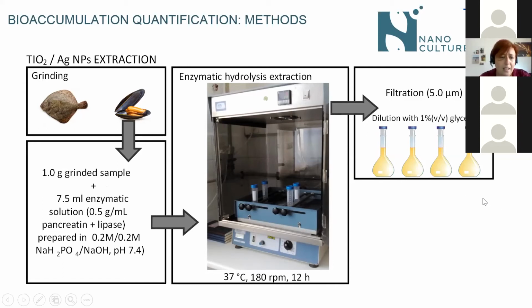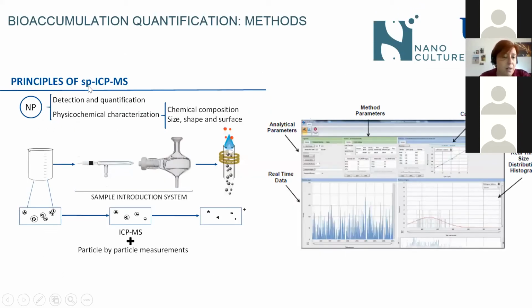And that's why we use mainly enzymatic digestions. Then we filtrate and we analyze using single particle inductively coupled plasma mass spectrometry. This complicated name of technique allows us to quantify nanoparticles by flowing the sample in the detector, and we will obtain peaks. These peaks correspond to the nanoparticles that are appearing over the detector, and the intensity of the peaks will correspond to the size of the particle.